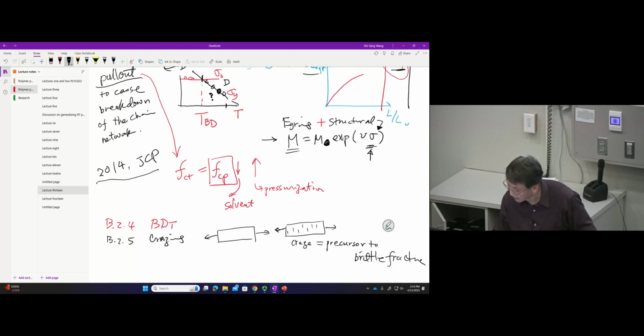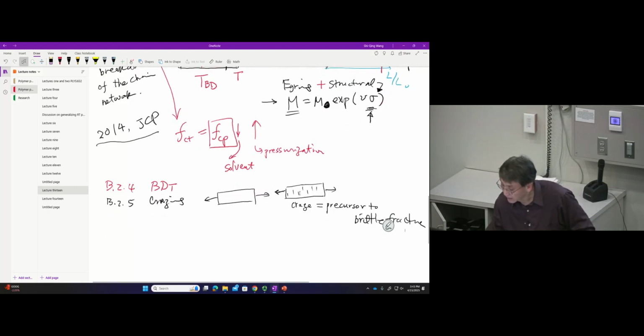The reality actually is more complicated. But in our picture, we all understood that this crazing is truly some internal breakage of the sample. The sample has achieved some separation inside, and this could be submicron, just less than a micron in size. And in our language, of course, it amounts to some breakdown of the network.